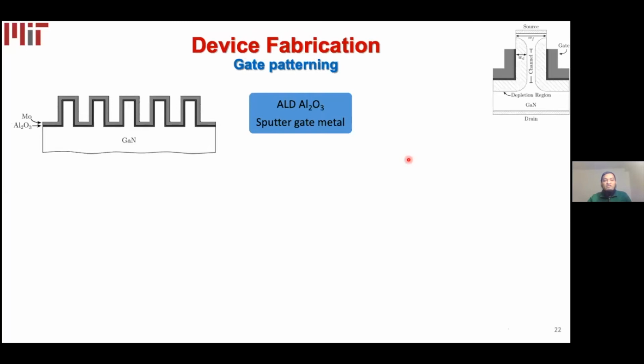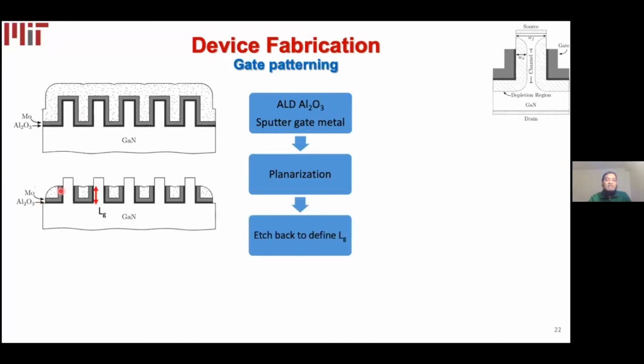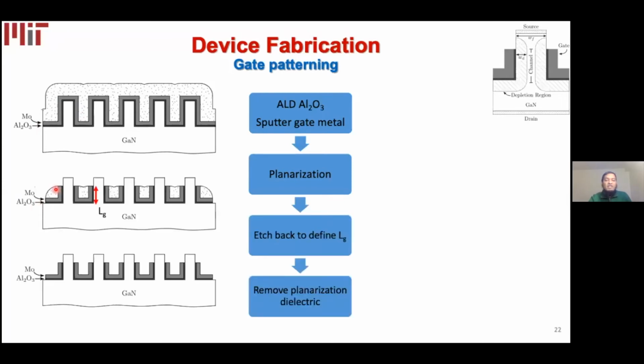And once we have the fins, our next step is the gate patterning, where we deposit, with atomic layer deposition, aluminum oxide wrapping around the fins, and we sputter gate metal on top of it. After that, we do a planarization and etch back to define the gate length. And finally, we remove our planarization dielectric, and then we have our fins with the gate oxide and gate metal.